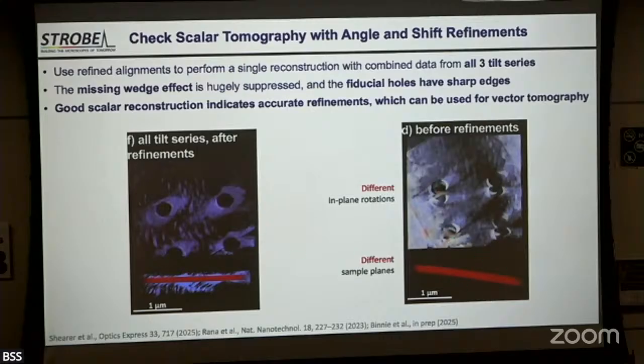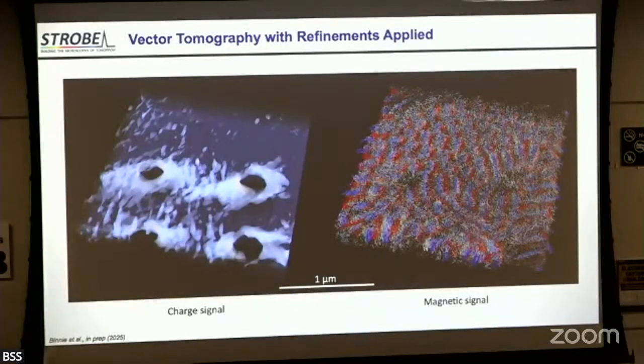In our initial efforts, you could see that the three tilt planes are not all the same plane. So the images aren't registered properly, and you can see the holes are shifted. So you could not believe the spin texture from that incorrectly imaged sample. But after three or four years, we can have the 3D spin texture. This was a mixture of stripe domains and skyrmion sample.